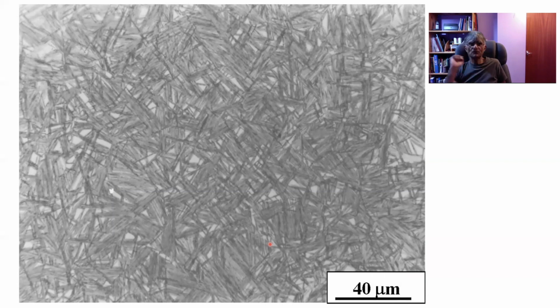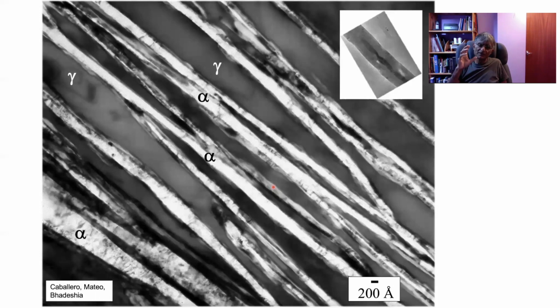So on its own, this doesn't look remarkable, but I want you to note that this structure is effectively isotropic, because I'm going to show you a very high magnification image of one of these regions, which can be completely misleading. So this is the breathtaking transmission electron microscope image showing the platelets of bainite and the carbon-enriched retained austenite. And this scale here is 20 nanometers. So these are approximately 20 nanometers wide, finer than this carbon nanotube at the same magnification.